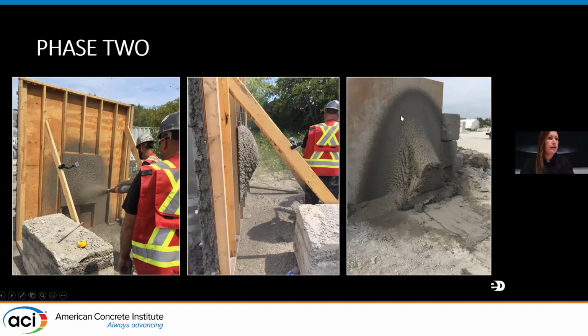And then on the right here, we have what is called the buttress test, indicating the stackability. Sometimes people refer to that as the benchability as well of the shotcrete mix by measuring the thickness and height to which the shotcrete could be stacked without sloughing.